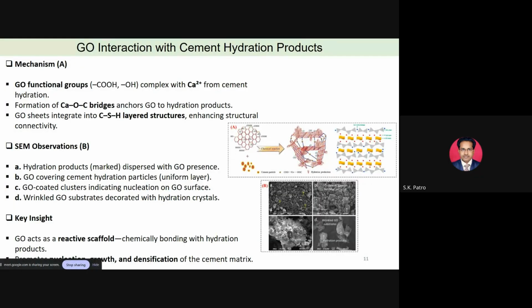See, when the graphene oxide interacts with the cement hydration products, CSH gel and calcium hydroxide, it develops some functional groups. These functional groups develop other functionals, and these functionals help in putting the proper bridge between the conventional ingredient and the nano graphene oxide. So that helps the formation of CaOC bridges, which anchor graphene oxide to hydration products. CaOC, these bridges, are calcium, oxygen, and carbon. These CaOC bridges anchor with GO for the development of hydration products.